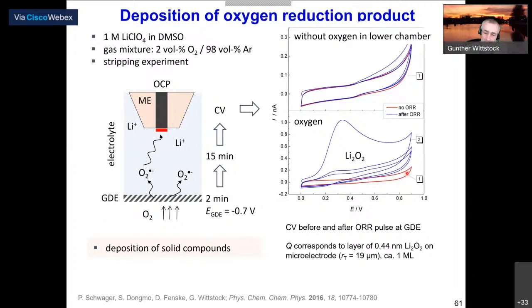If we have, however, oxygen in the lower compartment, and the gas diffusion electrode can really make oxygen reduction here, we make this for 120 seconds, and then wait 15 minutes to give enough time for the microelectrode to collect. And if we then do this experiment, we get a huge stripping peak for lithium peroxide. If we then take the charge and calculate, we come to about a monolayer.